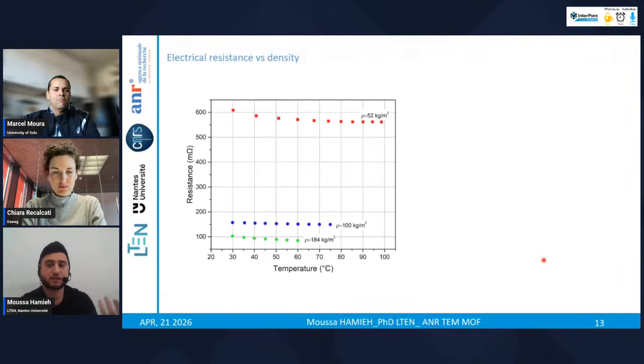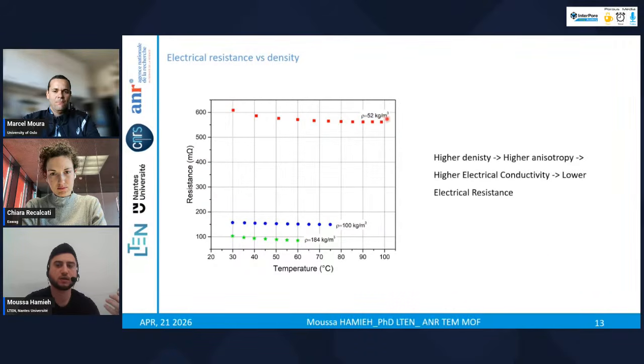To understand this behavior better, we look also at the electrical resistance of the material in the circuit as a function of temperature and for the different densities. And we see clearly that lower densities correspond to higher electrical resistance, and when increasing the density, we have lower electrical resistance because of higher electrical conductivity, and this explains the previous results.